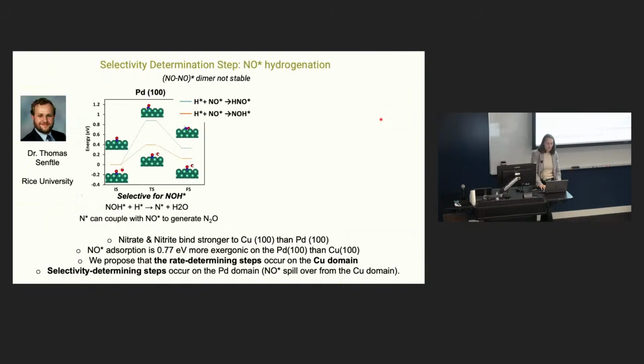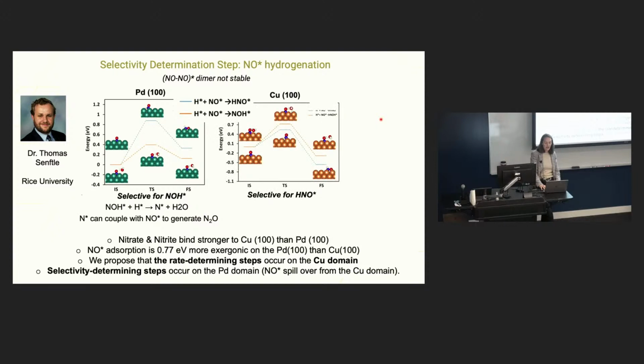Again, we worked with Tom to look at what was happening on these surfaces, and we looked at the theoretical underpinnings of the adsorption and reaction processes. The interesting thing that he found was that we are proposing there is some spillover effect, where you're binding nitrate and nitrite to the copper and the palladium, but the NO adsorbed species are able to spill over from the copper to palladium, and this is a really important step in making nitrogen. You need two NO species to couple to make nitrogen, and so by having that specific interface between the copper and the palladium, you're able to get that selectivity towards nitrogen.